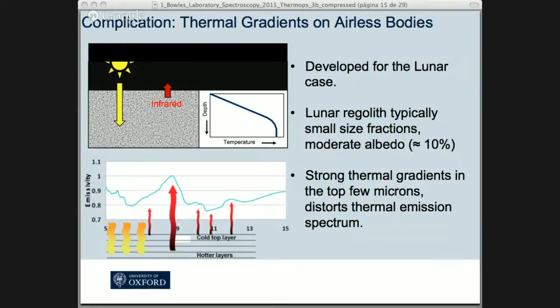And what that does is it starts pushing the shape of the spectrum around when you measure it. So this is a fine particulate measurement of, I forget what it was now, just an example spectrum measured a few years ago in our lab to show this effect. What you can see is that this approximately 8 micron feature, the Christiansen feature, is this region of very low volume scattering. It's where the refractive index of the mineral is essentially getting close to the refractive index of the material it's sitting in. So it's getting to about 1, and all of a sudden all the scattering gets reduced. That means you start seeing deeper into the sample.